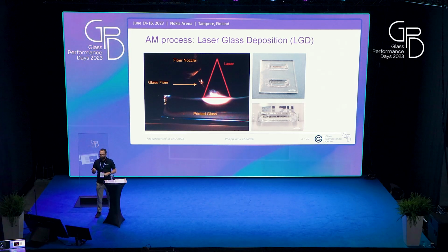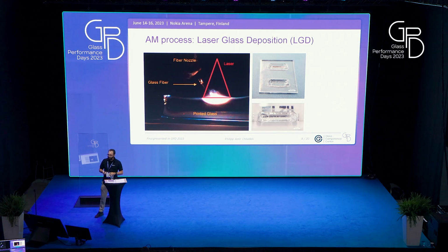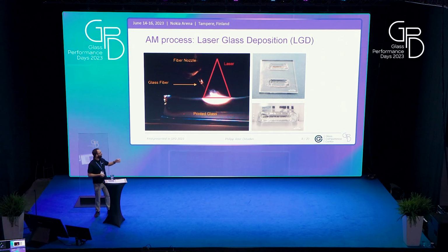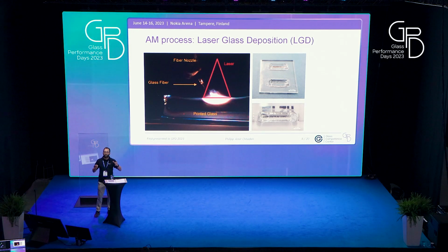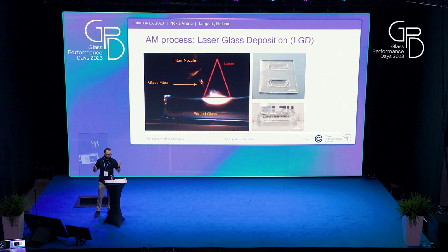where the glass absorbs the energy from the laser and reaches the viscosity in the range of this area of joining viscosity I showed earlier in the slides. With this, they managed to print those small walls on a glass plate, and this will be our specimen. As you can see, this is very small in diameter and size, which is common, as most of the current 3D printers are still small. They're printing on sheet sizes like a paper.